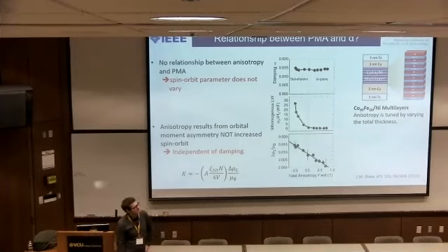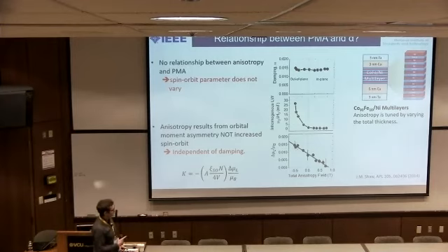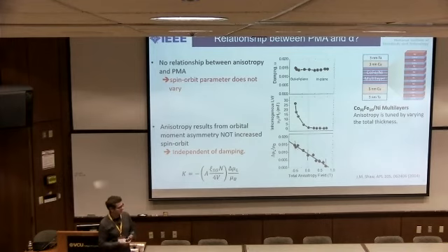I can't imagine that in some of the older literature, single crystals in spheres are measured. And I was wondering how your data compares. Well, the thing to take into account, though, is the g-factor along different crystalline axes was probably different as well. I mean, in permalloy, of course, it's very low anisotropy, and you may not expect a big difference. The other issue there is that most of those measurements were done with cavities, which is typically 9 point whatever gigahertz sort of frequencies.